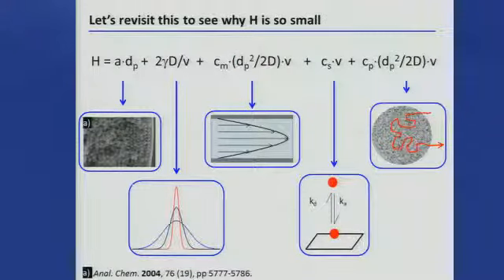But what we did was we went back and looked at all of the things that cause broadening, and we knew we were getting rid of this term. We had proven that it was less than 5 nanometers. We did that with electrochromatography. We didn't have any porosity, so we're using non-porous particles. So it had to be this term, this Poiseuille flow profile term. And this gives broadening because a molecule that's in the middle of the stream has a higher velocity than a molecule near the side. Now, some of this is averaged by diffusion, which is why diffusion is in the denominator here, but it never completely averages, so there's always some residual amount of broadening from that. And so this was the suspect term that was used in all of the theory.